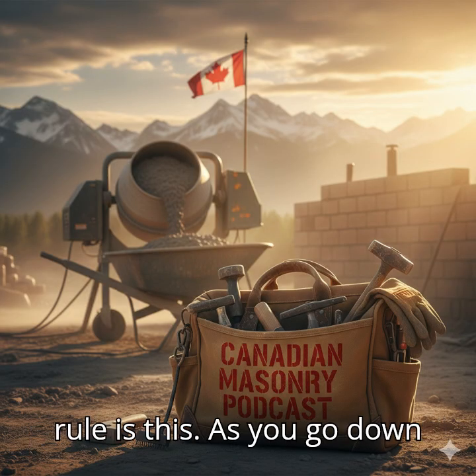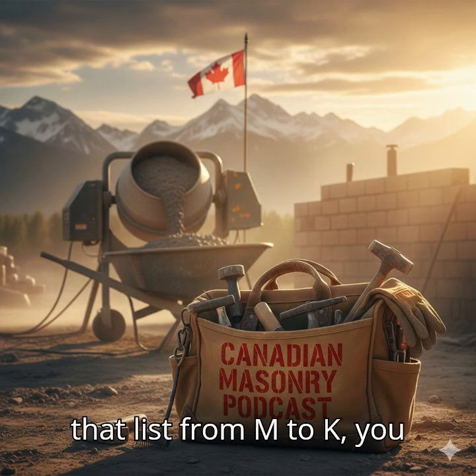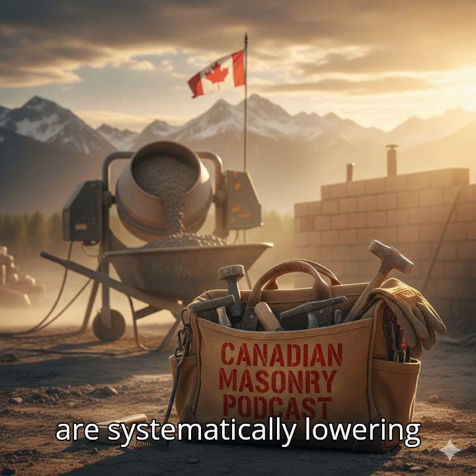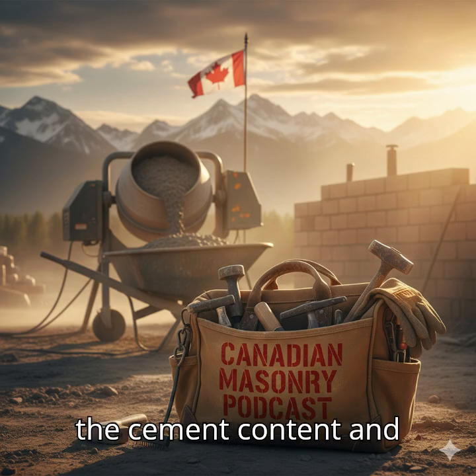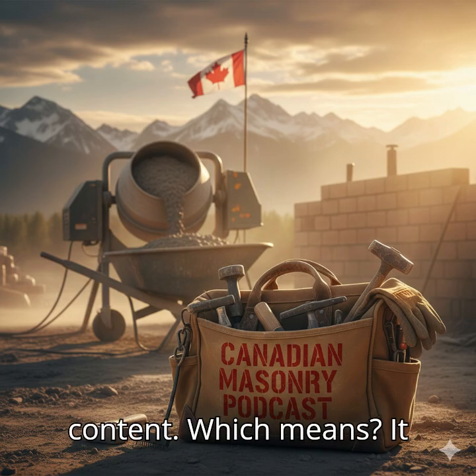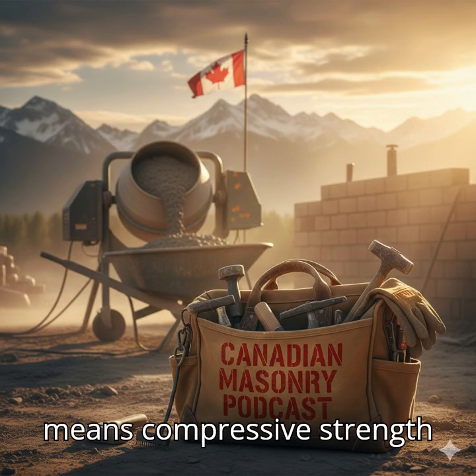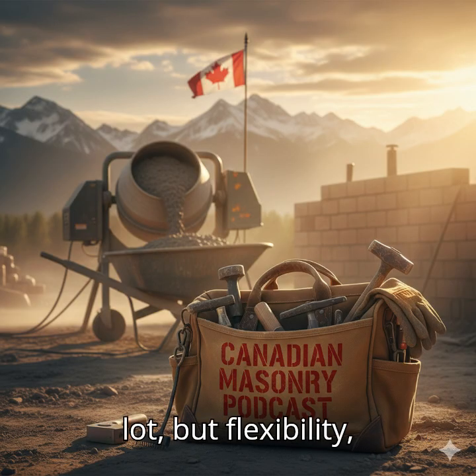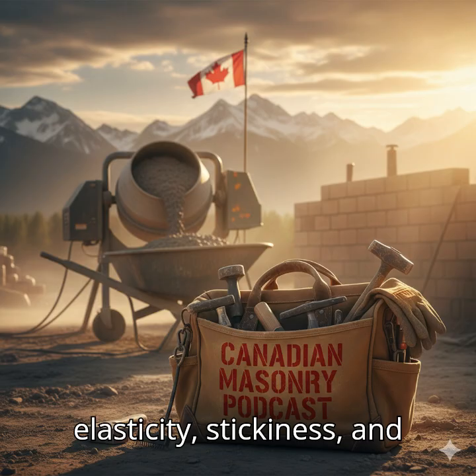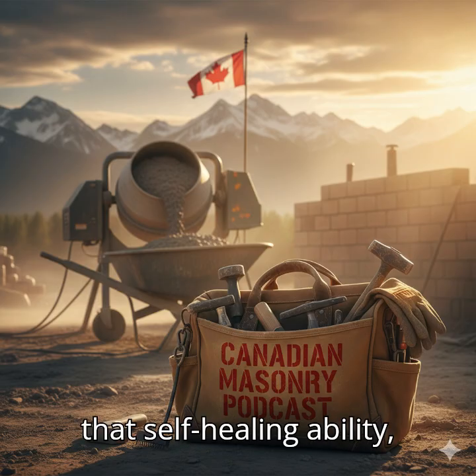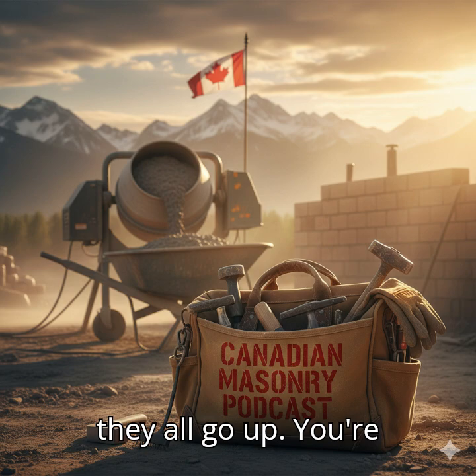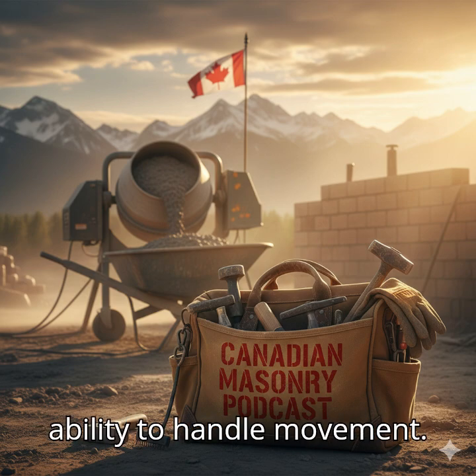The fundamental rule is this: as you go down that list from M to K, you are systematically lowering the cement content and usually increasing the lime content. Which means? It means compressive strength goes down, sometimes by a lot, but flexibility, elasticity, stickiness, and that self-healing ability, they all go up. You're swapping raw strength for the ability to handle movement.